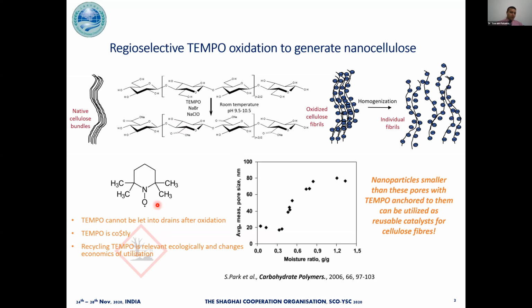However, if we ensure that TEMPO is anchored to a support that can be taken out easily from the reaction mixture, then the nanocellulose production can be made sustainable. I found out that cellulose fibers have pores up to 80 nanometers on their surface at certain moisture content. So I decided to anchor this TEMPO on nanoparticles which can penetrate the cellulose fibers through the pores on the surface, oxidize the hydroxyl groups on cellulose, and then come out of those pores from the fibers and be isolated easily without letting TEMPO into the drains.